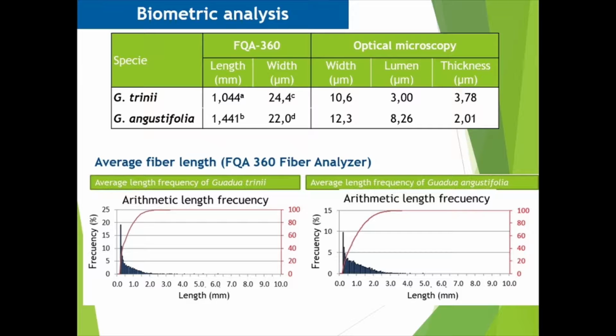As I mentioned previously, the determination of biometric data was carried out from a fiber solution, first using the FQA fiber quality analyzer, which gives length and width distribution of fibers. The average fiber length was lower for Guadua trinii. It was 1.044 millimeters for Guadua trinii and 1.441 millimeters for Guadua angustifolia. The average width of fibers was slightly higher for Guadua trinii. It was 24.4 microns for Guadua trinii and 22 microns for Guadua angustifolia.